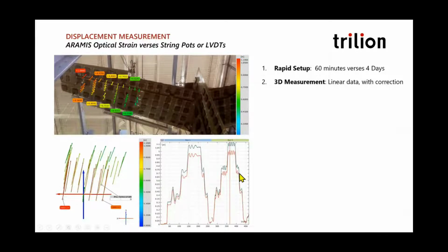Here's an example of a test that we were running. You're seeing the twist in the wing from the front to back. So there's line of sight measurement, no interferences like a wiffle tree touching a string pot line. You can choose the vertical, you can choose your reference in the field of view even after the fact. You can use the vertical stabilizer or some structure in the field of view as your reference for the measurements. In this case, we're using the structural floor of the building to do the measurement.